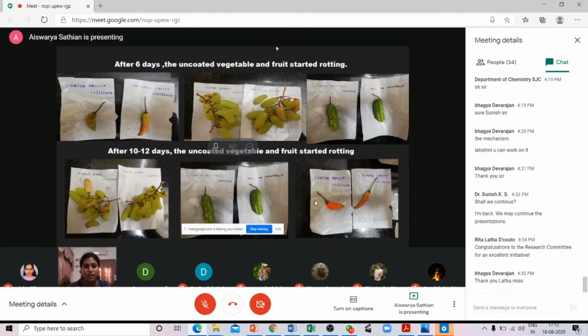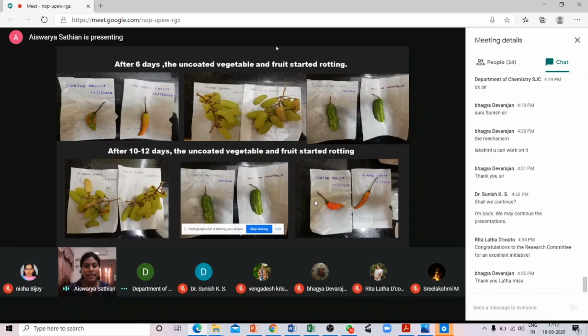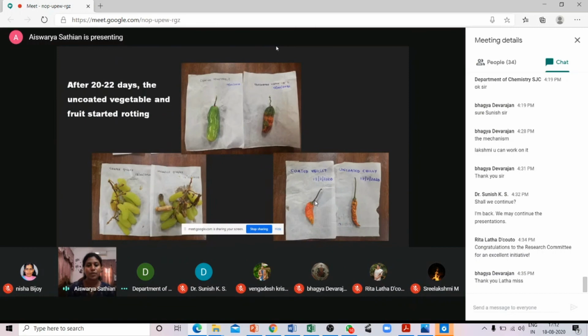I took the pictures after 6 days, and after 10 to 12 days, and this image is showing the rotting of the uncoated fruits and vegetables. When it comes to 20 to 22 days, the uncoated vegetable and fruit was rotten.